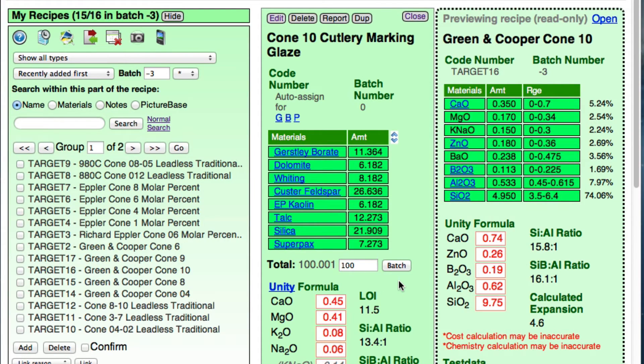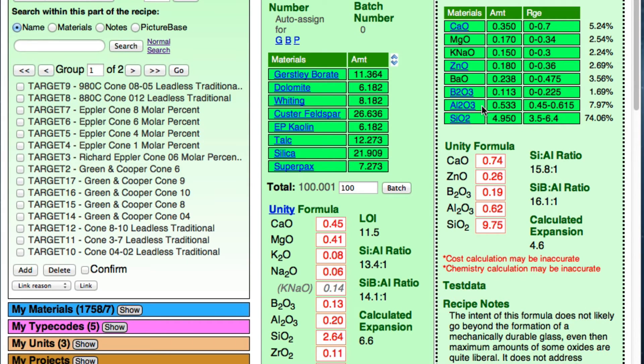Let's compare these oxides. First, MgO — the maximum is 0.34, and in our glaze it's 0.41, so we're way over. And the alumina, which is the oxide most important in establishing how hard and durable a glaze is going to be — the minimum is 0.45, and we have 0.2, less than half of that. The silica, which is the glass builder of the glaze — we obviously need plenty of that for a hard glaze. The minimum is 3.5, and we've got 2.6, so we're way off.